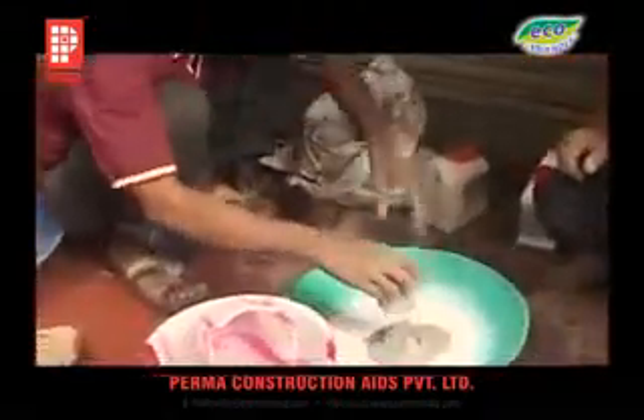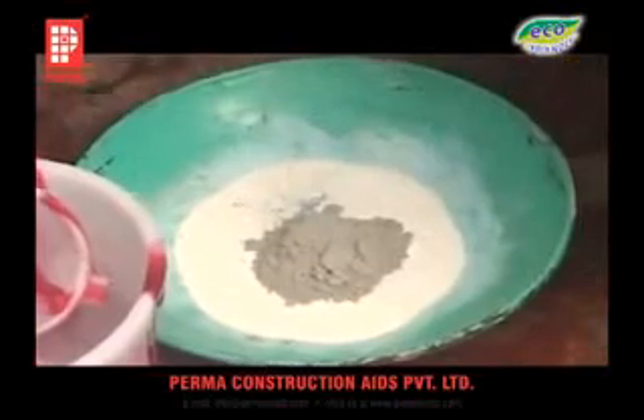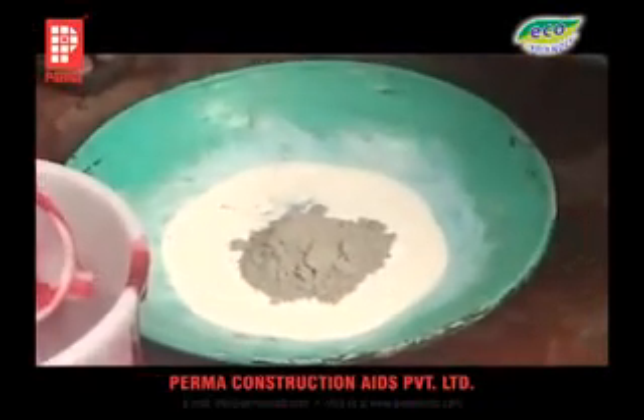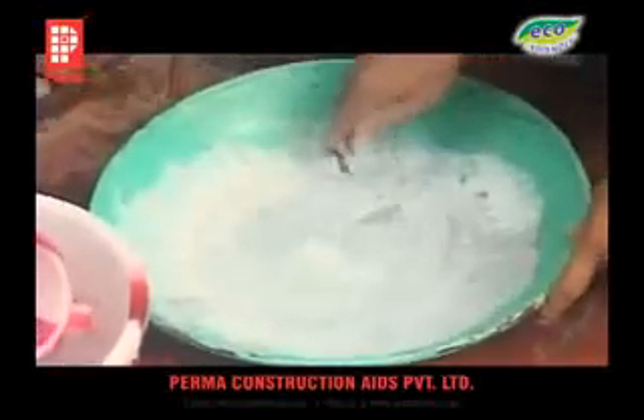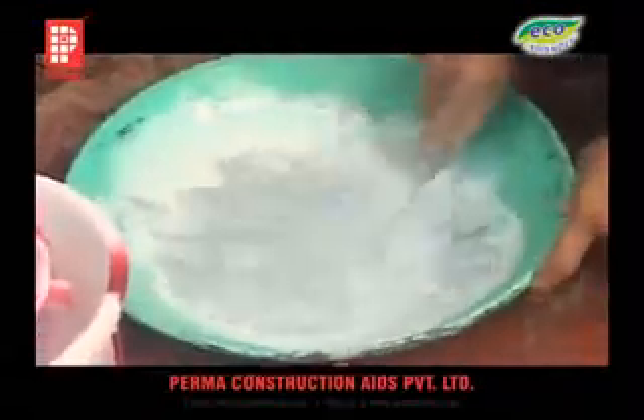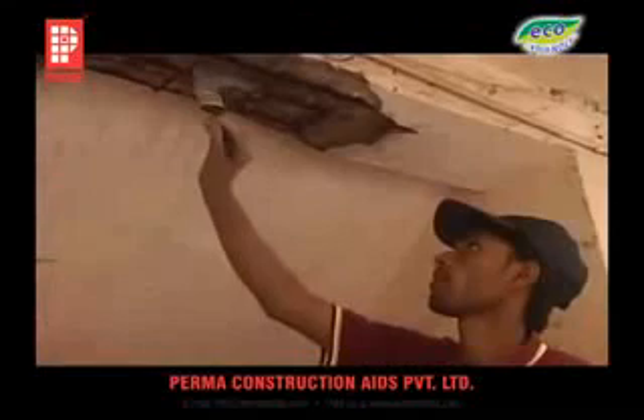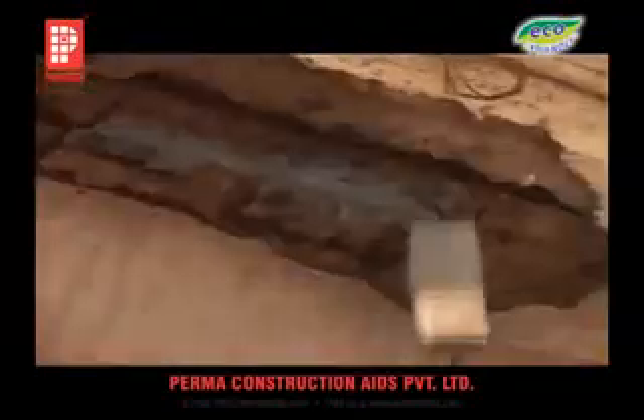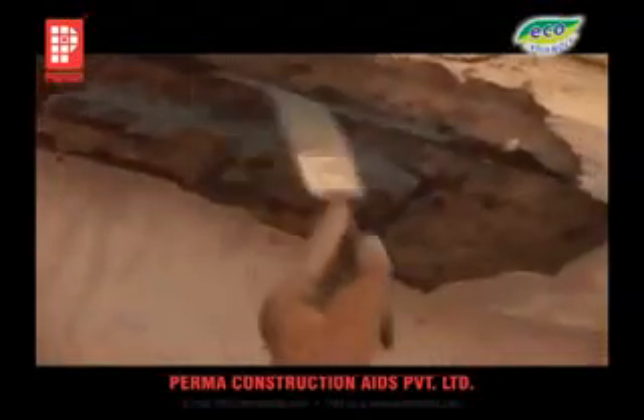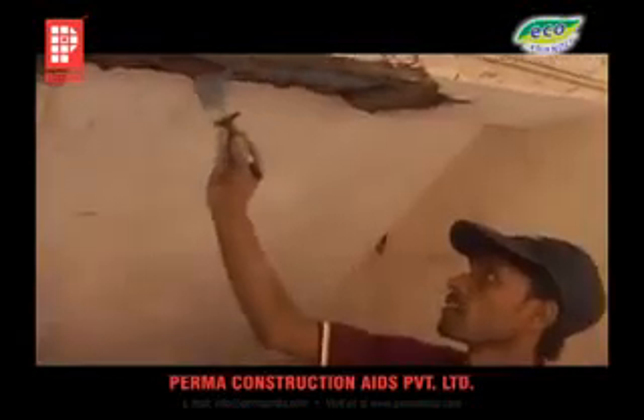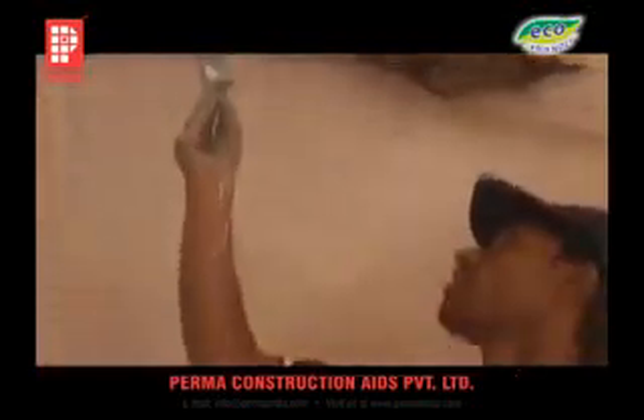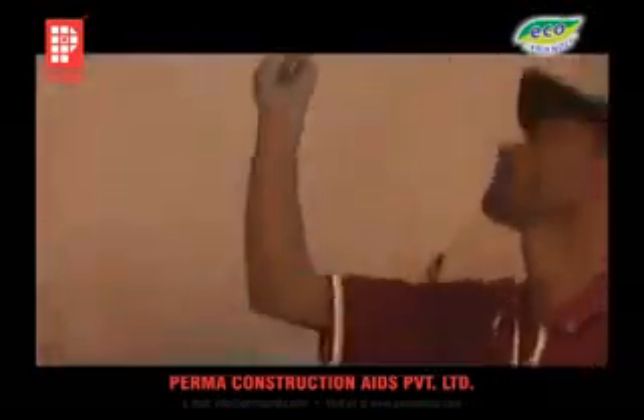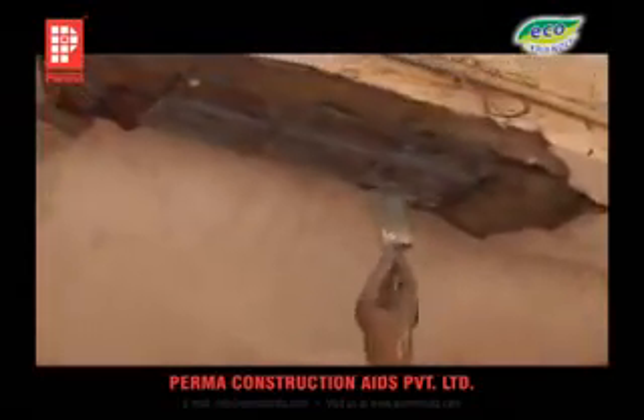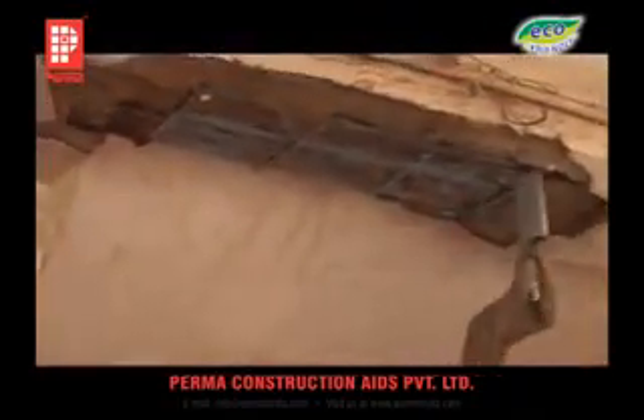Permabond SBR is mixed with cement in the proportion of 1:1 by volume. Here, 2 measures of SBR is mixed with 2 measures of cement. This slurry is brush applied on the cleaned, sound reinforcement and onto the added reinforcements if any. This coat acts as a passivator coat, or a coating that prevents further corrosion of steel in future.